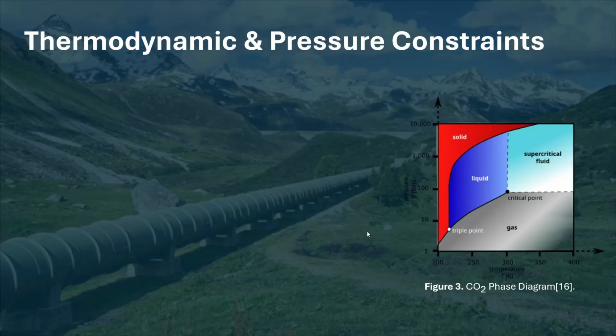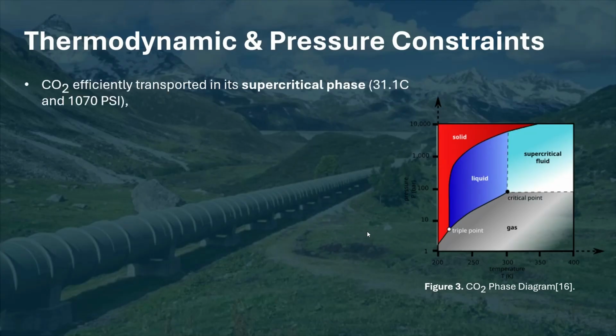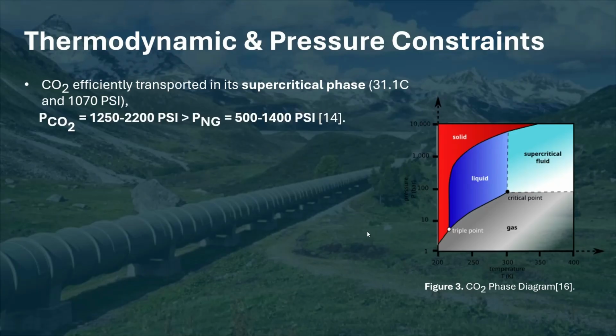So CO2 is specifically transported in its most efficient state if it's in the supercritical phase. Essentially, what that means is CO2 behaves like a dense gas. So it has a density similar to a liquid like water. I believe it's 50 to 80%. But it also has low viscosity, so it is still a gas. And so this occurs at 31 degrees and around 1000 psi.